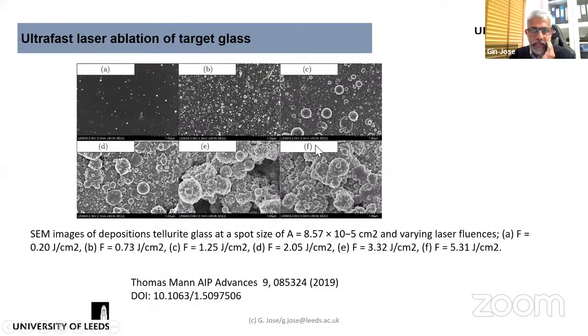So another way of looking at it is you look at ablated and deposited materials and see how the particle size is distributed at the surface. So this can be done with a simple experiment. You do a very short deposition so that there are no multiple particles coming up. So you get this, then you look at the substrate at different fluences, and look at the particle size distribution at the substrate to see what's the best fluence to go for.